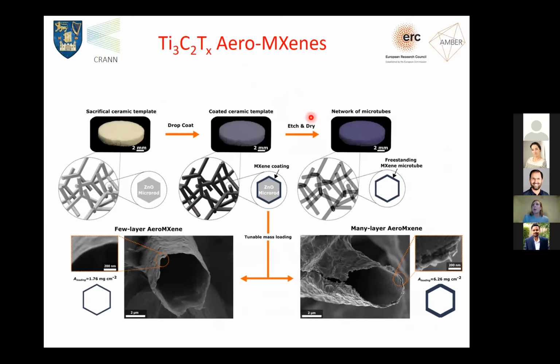Another very, very nice type of processing that we have managed to make with MXenes has been to combine it with this technology that is quite corroborated, using some sacrificial ceramic templates based on zinc oxide nanorods, and then literally dip them into MXenes solutions, and what you get is the MXenes start coating the zinc oxide nanorods. So all you need to do at that stage is to etch the zinc oxide nanorods away, and all you end up with are beautifully hollow structures made of MXenes. The nice thing about these structures is that they're pretty much 99% air, and they're basically hollow, and we call them aeroMXenes for this very reason.